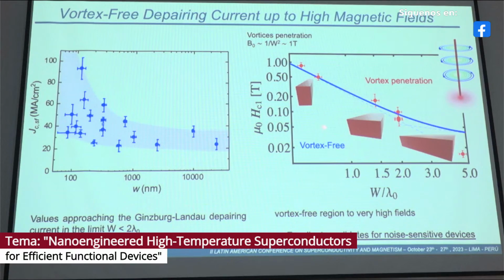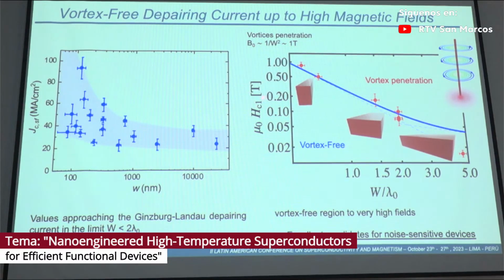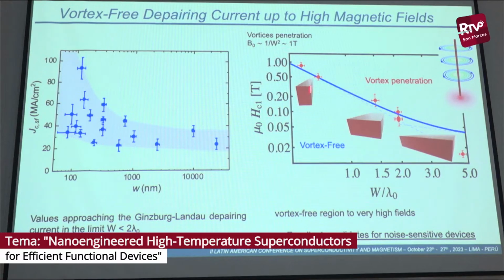And we have seen that here, in fact, what we have is a region where the nanowire doesn't have any vortex inside. And here I plot the value of Hc2, which has been calculated from the position where we have the first vortex inside of the system. And we see that this Hc2 scales with the width of the nanowire, and we have in the very, very narrow nanowires up to 1 Tesla without any flux penetration, which means that we can have a very wide region of magnetic field where we can play with the system applying currents without flux penetration.